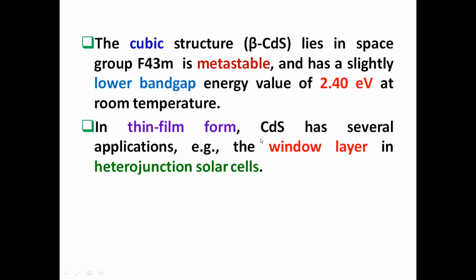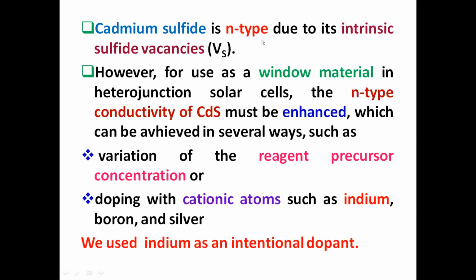Thin films of CdS have several applications, especially as window layer in heterojunction solar cells. Cadmium sulfide is an n-type material due to its intrinsic sulfur vacancies, Vs. However, to use it as window material in heterojunction solar cells, the n-type conductivity of this material must be enhanced, which can be achieved by several ways. From these ways, the variation of the reagent precursor concentration or doping with cationic atoms such as indium, boron, and silver. In this work, we used indium as an intentional dopant to produce thin films of cadmium sulfide.